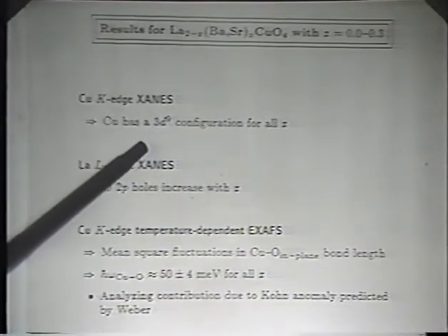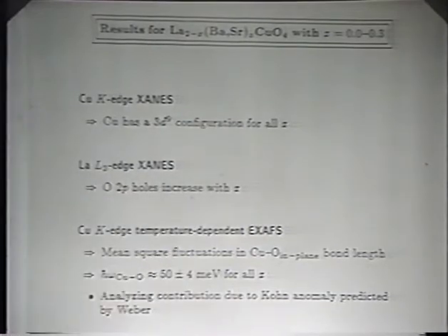People have been asking the question tonight, what's the copper valence? If you want to call it a valence, we'd say it's 2+. The important thing is a 3d9 configuration. This doesn't agree with band structure calculations, which would suggest that half of the copper d hole goes onto the oxygen, so that copper would be 3d9 plus a half, roughly.